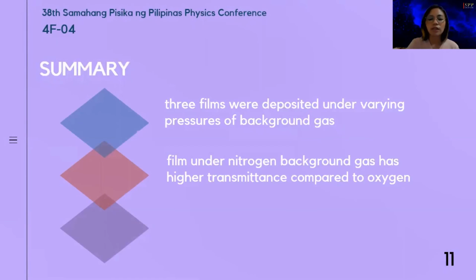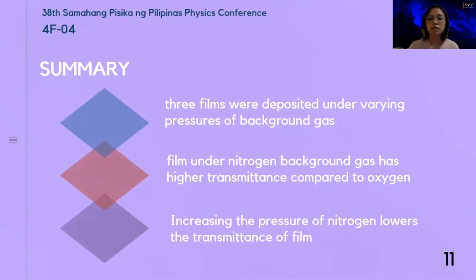On the other hand, increased surface roughness produced by the interaction of ablated materials and oxygen causing sputtering can explain the lower transmittance of the optical energy on films deposited with oxygen background. And lastly, increasing the pressure of nitrogen background gas, which can be explained by a possible increase in surface roughness of thin films, lowers the transmittance.